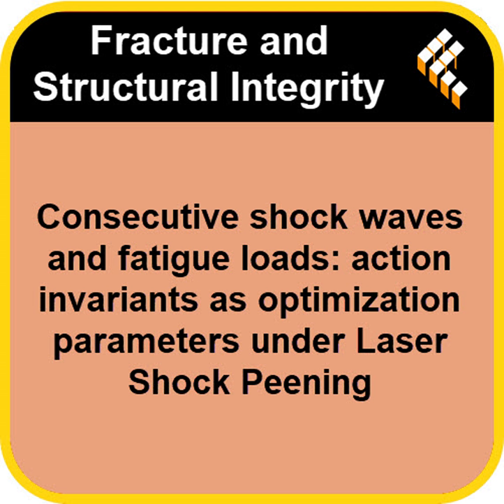It does seem odd at first glance, but think about what the initial shock did. It created a very high density of fine-scale damage, intense dislocation networks throughout the material. It sort of pre-fragmented the microstructure. Okay. So when the fatigue crack eventually tries to grow through this pre-fragmented structure, it can't easily follow nice ordered paths along crystallographic planes, which normally creates rougher surfaces. It can't form those typical ordered defect structures like persistent slip bands as easily.